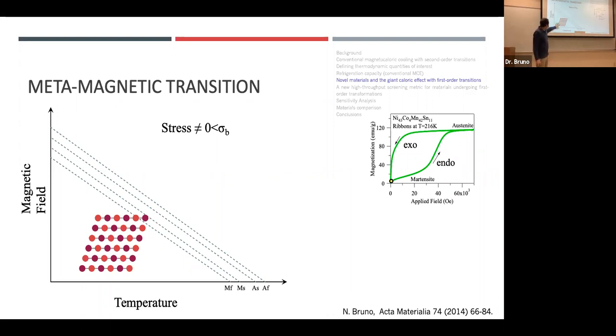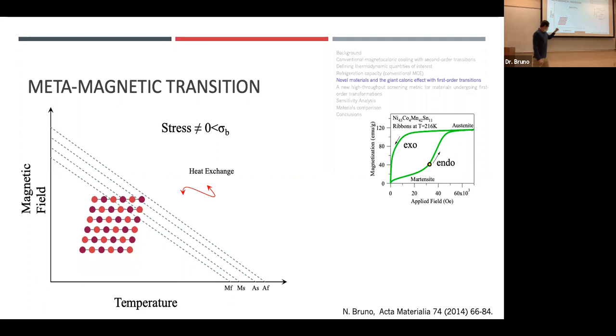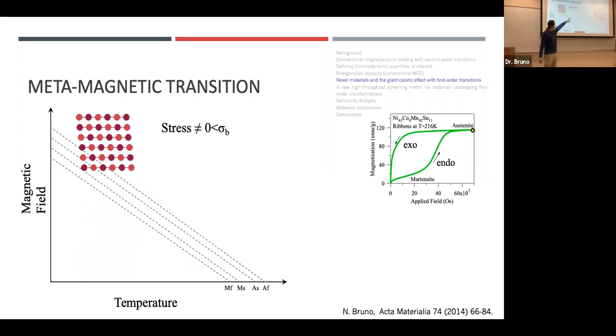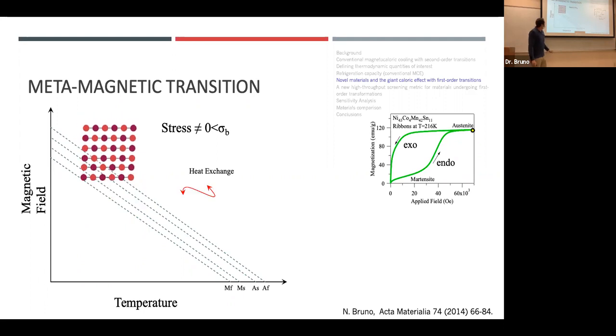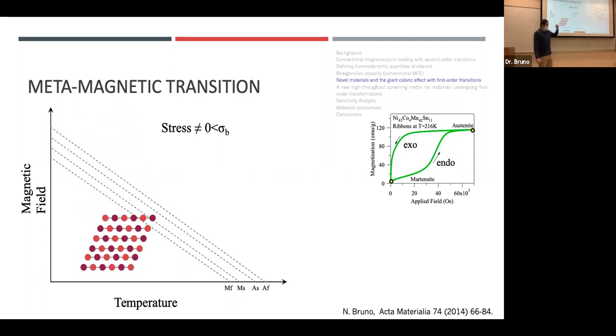So here we have martensite. We apply a magnetic field. We'll magnetize martensite, which is usually non-magnetic. Then we'll push it into the austenite phase, and we get that heat exchange, right? That latent heat of transformation. When we release the field, we go back to martensite. This is a reversible martensitic transformation.